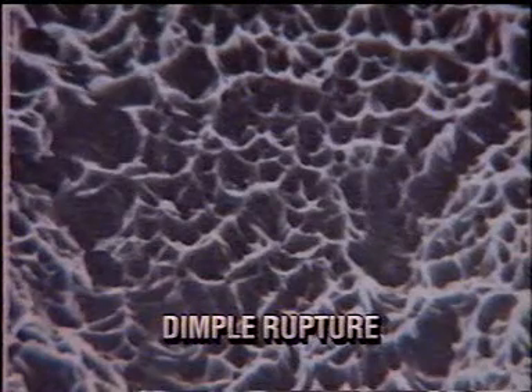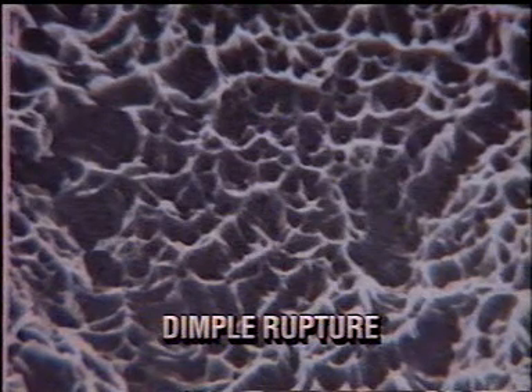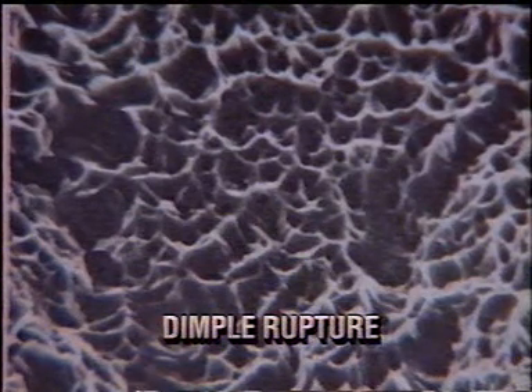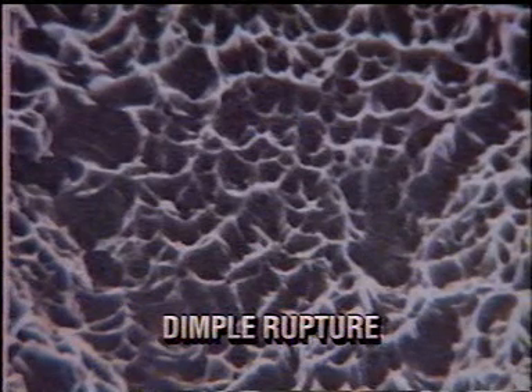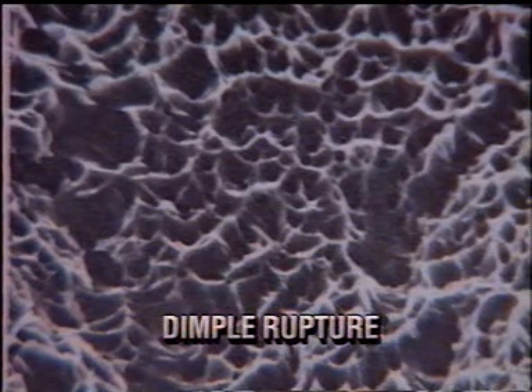With an SEM, a scanning electron microscope, the fracture surface of a dimple rupture exhibits tiny cup-like depressions. These are the dimples, which are the microvoids torn apart during the rupture process. The size of the dimples on a fracture surface is governed by the number and distribution of microvoids that are formed. When these nucleation sites are few and widely spaced, the microvoids grow to a large size before joining. The fracture surface then contains large dimples. When many microvoids are formed and adjacent microvoids join before they have an opportunity to grow to a large size, the fracture surface contains many small dimples.